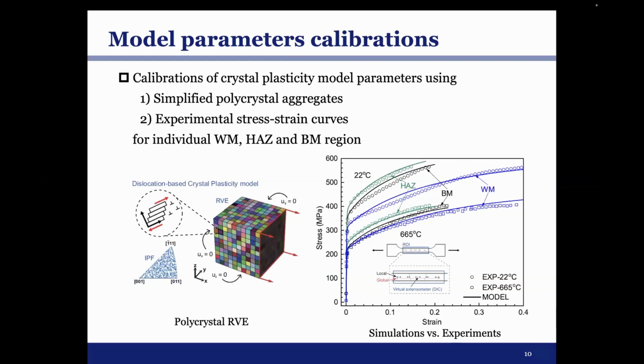So first of all, we need to calibrate such a crystal plasticity model. The first thing we do is to run finite element simulation using such simplified polycrystal aggregates to fit the stress strain curves that we obtain from the tensile test. And as we can see here, there is a good agreement between the experiment and the simulations for two temperatures, room temperature and 665 degrees.